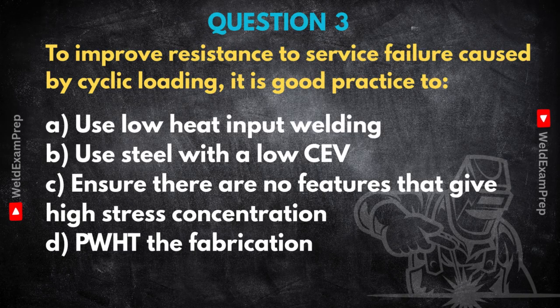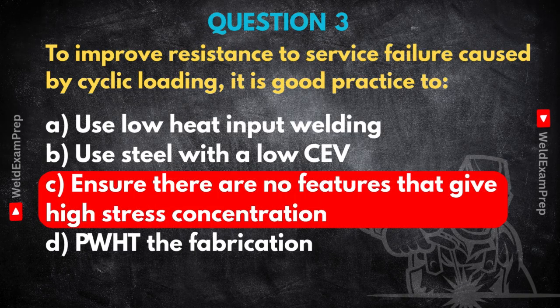Right, the answer is C. Ensure there are no features that give high stress concentration. Yes, definitely. When you hear cyclic loading, you should immediately think fatigue failure. Right, the big one. It's probably one of the most common failure modes out there, especially in structures that see repeated loads. And the absolute key here is that fatigue cracks nearly always start at stress concentrations. Stress raisers. Exactly. These can be tiny flaws, or they can be design issues: sharp corners, sudden changes in thickness, weld toes that aren't smooth, even things like rough grinding marks.